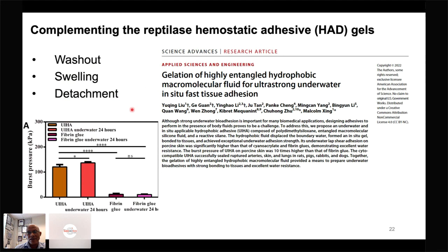So we were able to address these issues that we observed in the previous study in this follow-up study. And these are just some of the adhesion strengths. So you can see that you can take this underwater in situ hydrophobic adhesive, and once the adhesion is formed, you can put it in water for 24 hours, and then you measure the adhesive strengths, and you can see that, in fact, it improved compared to the one before. With fibrin glue, you can see that the adhesion strength is low to begin with, and then after 24 hours, there is no improvement. So it's another exciting study on this one. I'm just going to show you a couple of videos on this one.